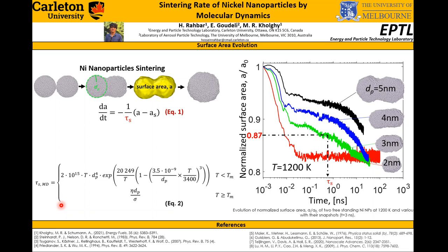It was found that the sintering rate is highly dependent on the size of particles. In other words, smaller particles result in a faster sintering. The reason relies on the fact that small nickel nanoparticles, typically with a diameter less than 5 nanometer, undergo recrystallization and surface melting during the sintering.